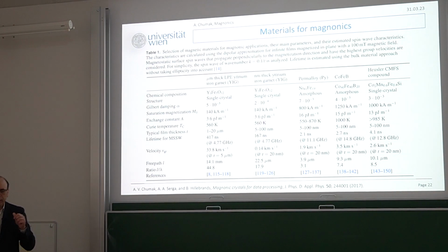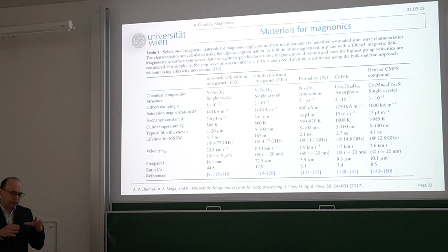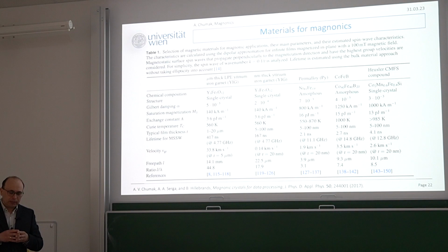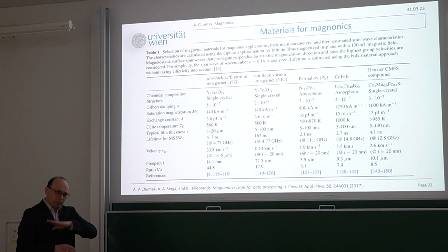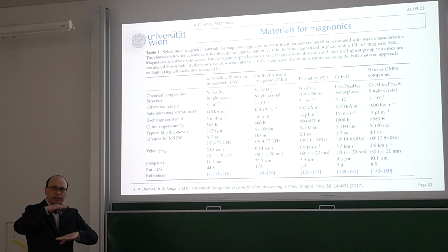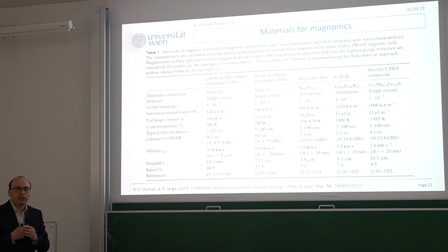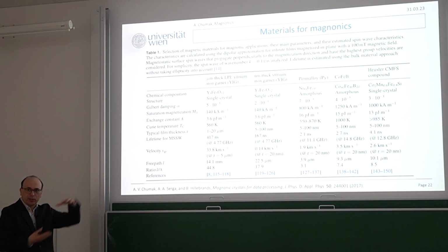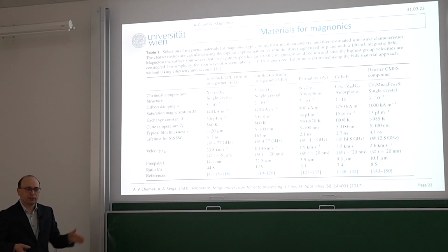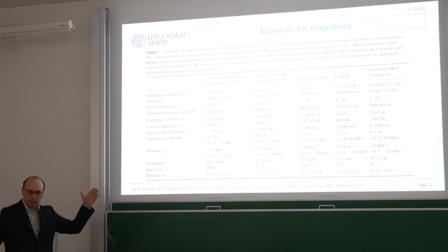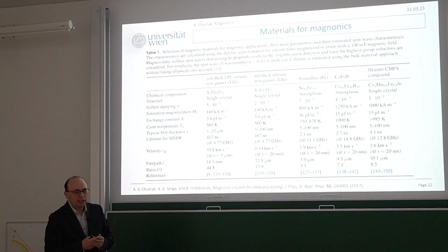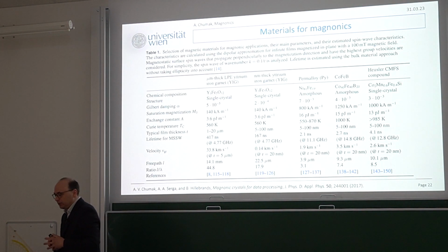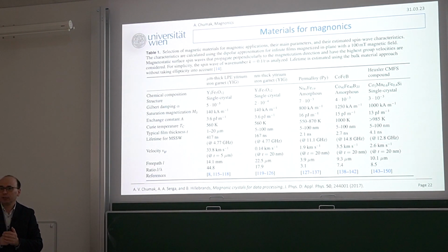mechanisms which are taking place inside of the sample on some impurities, inhomogeneities, defects in crystal structure, but also on the surface. Bottom surface on GGG and top surface. And then, of course, the volume-to-surface ratio matters. So if you have a very big sample, the surface, just two of them, doesn't play so much role. But when the volume to surface ratio is getting very small, then surface scattering is also getting important.